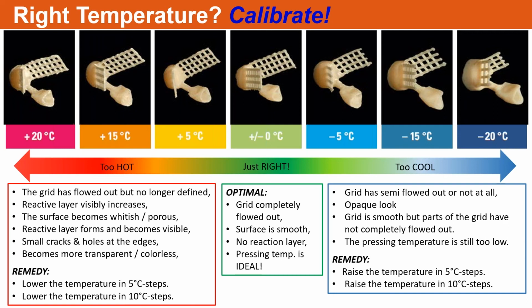And then if you go too high, it really starts messing up the color, but also you have the breakdown of that investment. You have the roughness that's showing up, and what we don't want is excessive reactive layering, that whitish material, and then we have to go to maybe a chemical compound to break down and remove that residual reactive layer. So we want to make sure that we are within the zone that is just right. So there are test methods.